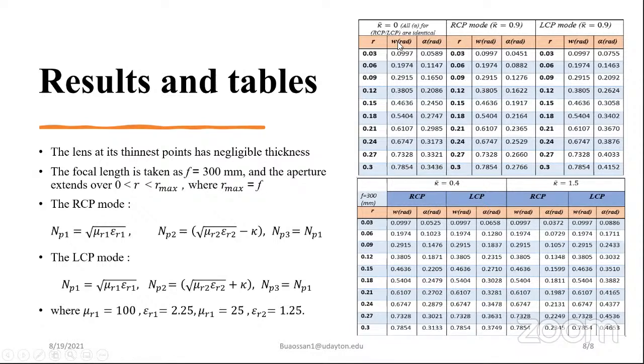We can see here that by making kappa equal to 0, both RCP and LCP are identical, but by changing the kappa value, we find different incident angles for the RCP and LCP polarizations. To get a 300 millimeter focal length, changing the kappa value changes the incident angle for RCP and LCP. I would like to thank you. In the poster, you can find all the cases that I studied; I showed some of my results. Thank you so much.